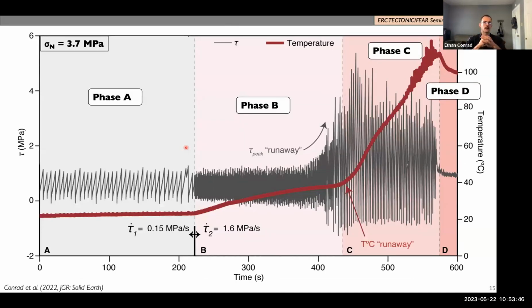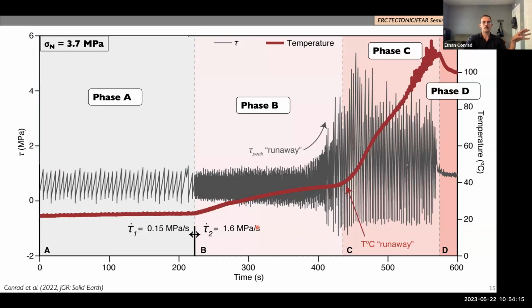Okay, back to this experiment with PMMA and the experiment we're going to discuss for the rest of this talk, essentially. So we've divided the evolution of this experiment into 4 different phases. The first phase occurs when we have this lower loading rate of 0.15 megapascal per second. And the second phase is when we have the higher loading rate, and that follows into phases C and D, the third and fourth phases. So we'll talk about those one by one and step through those.